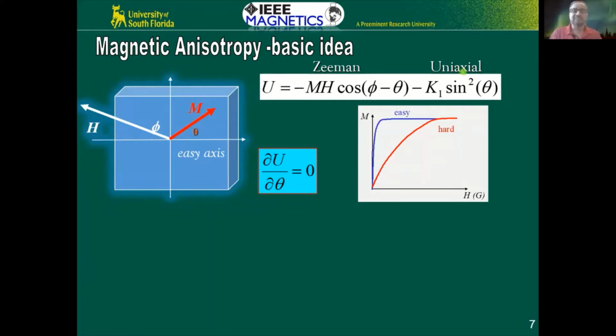So when you apply the magnetic field, of course, there's going to be a competition between these 2 energies. You can minimize the energy. I know you can do calculus, right? You can minimize the energy. And essentially, this here determines the shape of the magnetization curve. And this energy difference is what determines whether you can magnetize a material very easily at small fields, or it takes a much larger field. And this is nothing but the easy direction and the hard direction, right? So the shape of the MH curve, or what we call the hysteresis loop in a ferromagnet, depends on these competing energy scales, and it depends on anisotropy.